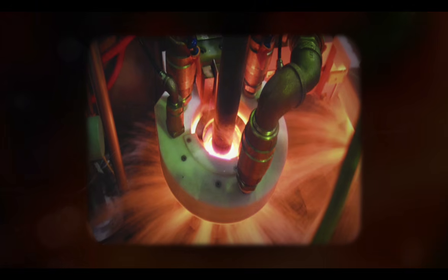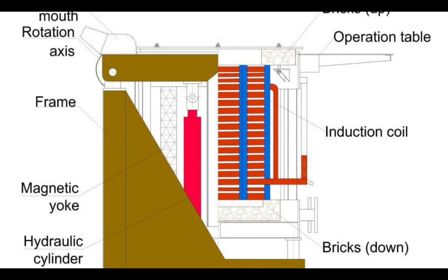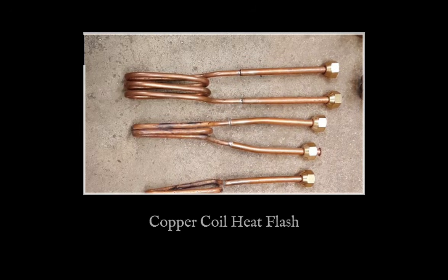When liquid metal reached the copper coil, the sequence that followed was governed entirely by physics, and it ran faster than any human response could match. The induction coil was hollow copper tubing, water-cooled at a continuous flow rate to protect it from the heat generated in the coil itself during operation. When liquid steel at 2,800 degrees contacted the copper, thermal conductivity transferred that temperature to the water inside the tubing in a fraction of a second.